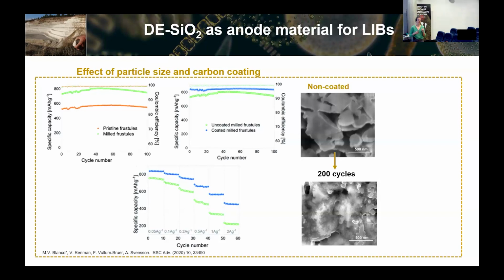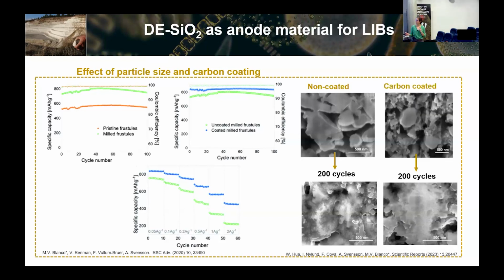For the particles that were coated with carbon, we can see that at least the particle morphology, the particle itself, was preserved as a whole, even though we have a lot of crack formation, islands where the material didn't react so well, and so on. So this is part of it. At some point, it's silicon that is causing this capacity loss.